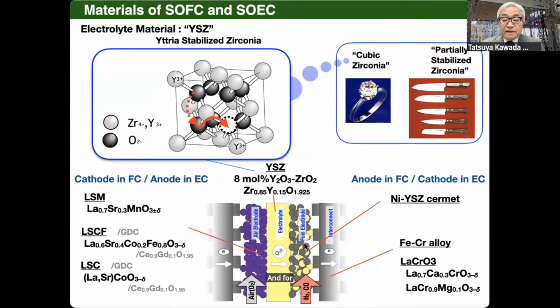For the fuel electrode side, we use nickel mixed with YSZ particles, so it is used as a ceramic and metal composite. Nickel YSZ cermet is the typical fuel electrode material. For the air electrode material, we use various types of perovskite oxide ceramics, so we use porous ceramics here. The typical ones are lanthanum strontium manganite, lanthanum strontium cobalt ferrite, or lanthanum strontium cobaltite. These are the most typical air electrode materials. Depending on the operation temperature, people choose one of those materials.